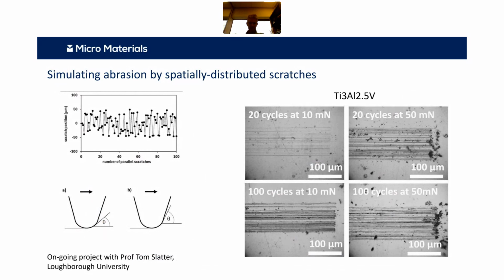What we can see on the example there on the right is that the top two is showing 20 cycles and there's a change in load. So as we change the load from 10 millinewtons under these conditions to 50 millinewtons, we're getting a transition from top left, where you'll see that set of 4, you're seeing hardly any damage, to suddenly getting much more damage and this debris, and that's due to a transition in the attack angle. So there's promotion of this transition to cutting at lower angles when you have these multiple structures, when you have residual stress fields and pile-up affected by previous scratches. So it's a much better test. In many ways, it's a much more reliable and useful test than just doing scratches in the same position.